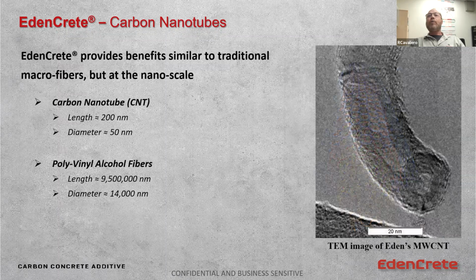One of our carbon nanotubes is anywhere from 10 to 50,000 times smaller than one piece of hair on your head. So here we have a transmission electron microscope image of a carbon nanotube. It's just able to blast through and generate the cross section. But you can see these striations in the circumference here that indicate the individual walls. And you can see the hollow core section, right?